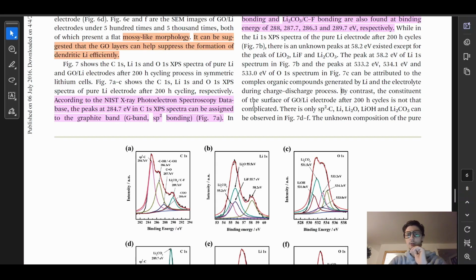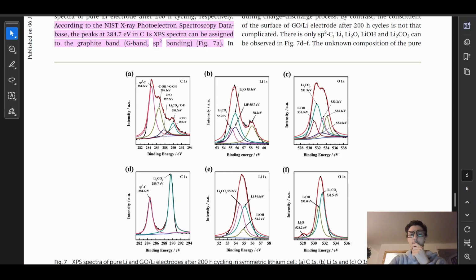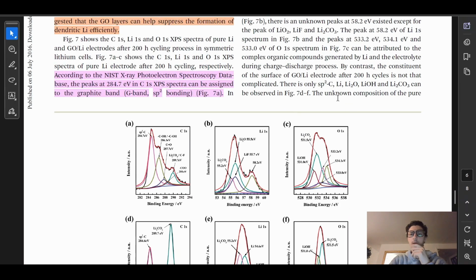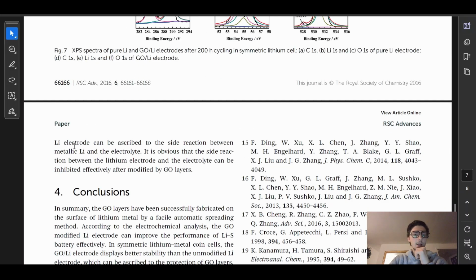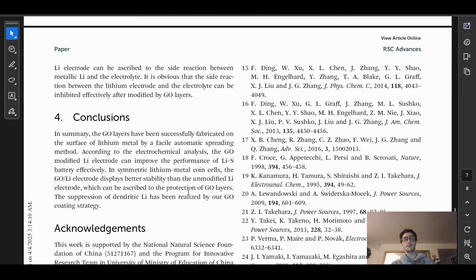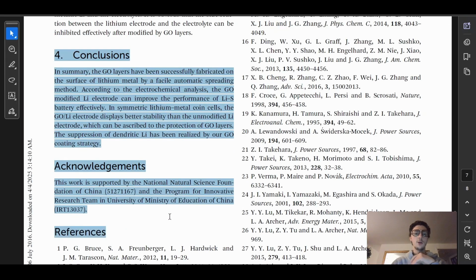By contrast, the constituent of the surface of the graphene oxide lithium electrode after 200-hour cycles is not that complicated. Okay, there's only sp2 C, Li, Li2O, LiOH, and Li2CO3 can be observed in figure 7D to F. Okay, interesting plots. I actually don't know what these are saying. We're gonna look at them more deeply. The unknown composition of the pure Li electrode can be ascribed to the side reaction between metallic Li and the electrolyte. It is obvious that the side reaction between the lithium electrode and the electrolyte can be inhibited effectively after modified graphene oxide layers. And that is it for the third and biggest section. And actually, we're done the whole article by reading this.